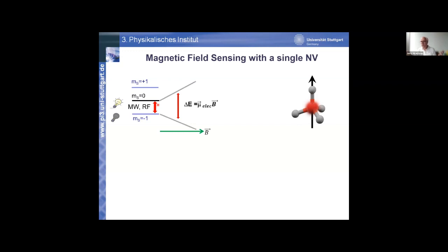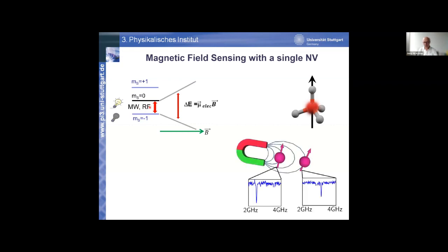All right. So this is very much as it is in atom vapor magnetometers, for example, a very similar technique, except that there you would not need to use microwaves. If you now put your sensor in an inhomogeneous magnetic field, then this spin transition would occur at different frequencies. That's what you see here on the left and the right. This is the frequency axis, 2 to 4 gigahertz, and you see these dips occur at different frequencies. You can measure these frequencies, and then the difference between nu1 and nu2 gives you a rather direct measurement of the magnetic field.